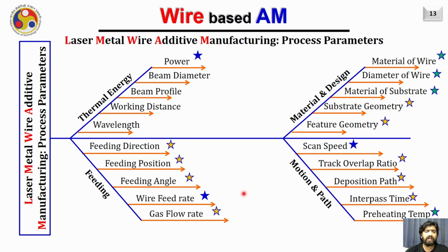So what we are seeing here are the three main parameters, like I already mentioned. For a particular part, if the CAPP is already defined, the parameters in the hand of the user are typically the laser power, the wire feed rate, and the scanning speed. Typically, these three parameters are sufficient to take care of the deposition quality and the metallurgical and geometrical quality of the deposited beads.